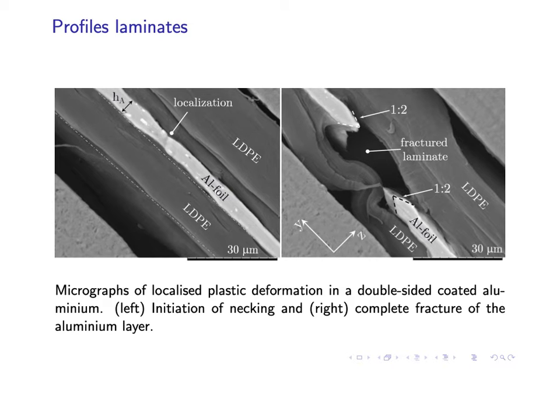And in the picture to the right, the cut is taken across the crack, and you see the aluminium foil is already broken. You can see the characteristic 1 to 2 slopes that you see at the tip that comes if you have necking, pure 45-degree shear plane type of necking, and in this case the polymer is broken on one side and not on the other.